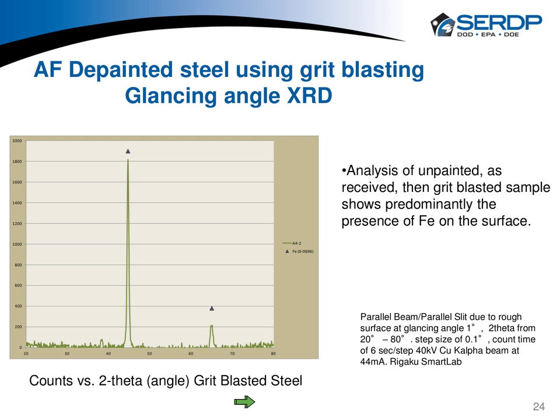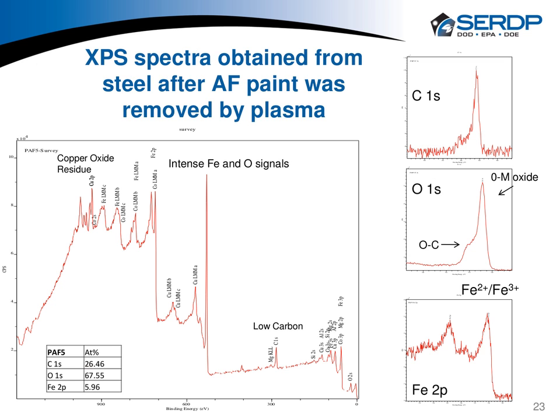Well, let's compare that to, oops, went too far, sorry. Let me go back here. Let me go to this one. This is the same type of sample, anti-fouling paint, but in this case, the paint was removed with plasma. Well, immediately notice that there are a lot of fairly high intensity peaks up in this region. Most of those are related to iron, and if we look at the atomic concentrations, about half the amount of carbon.